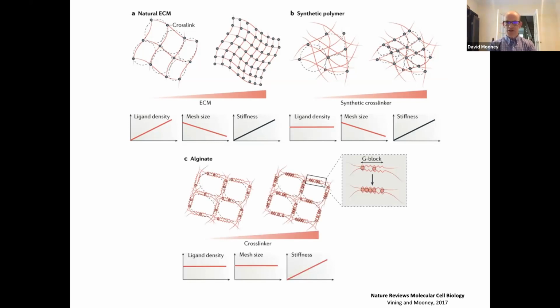So a really nice feature of these alginate polysaccharides relates to this mode of cross-linking that I referenced on the last slide. When they are put in solution and a small amount of cross-linker is added, you'll get divalent cations occupying a few locations within these G blocks of adjacent polymer chains, more or less aligning the structure of the network. And then as more calciums are added, you get more crosslinks formed, but you don't change the network topology. Instead, you basically just fill a few of the holes that are already lined up. So with this system, you can keep the ligand density exactly the same, the mesh size exactly the same as you change the stiffness. So it's a really nice system to decouple these variables.